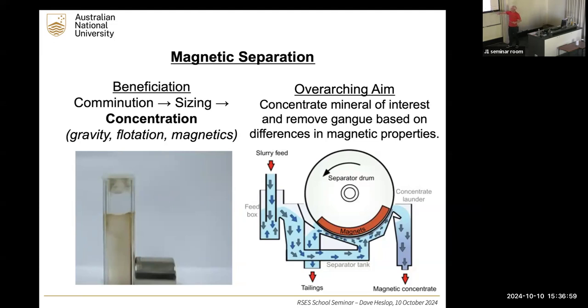If you have an iron-bearing mineral in the slurry, it has an attractive force towards the magnet. It gets stuck on the edge of the drum and gets rotated around until it meets the edge of the magnet where the magnetic field drops away. Then it's no longer attracted to the drum and it falls into this magnetic concentrate. The non-magnetic particles are not feeling any attractive force, so they get flushed through the system. Because this exit is higher than this exit, they tend to get flushed through into the non-magnetic component.